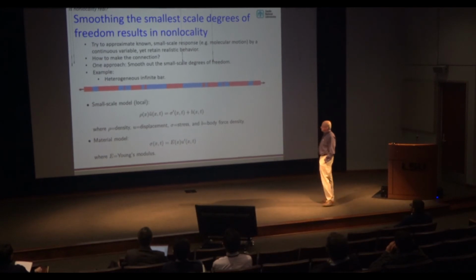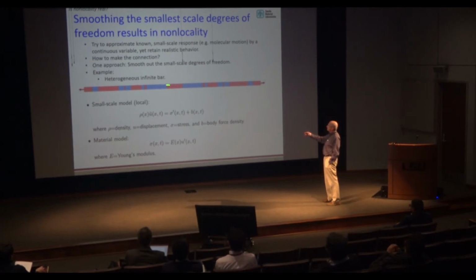So to look into whether non-locality can still be valid in such a case, I looked at the problem of an infinite bar with heterogeneities, which are what these blue and red stripes are supposed to represent. And we'll model that with the local theory at the small length scale. So the blue and red stripes have different values of Young's modulus, which is explicitly a given function of position. So here's the material model. Here's the small scale model, which is just the usual local differential equation of continuum mechanics.